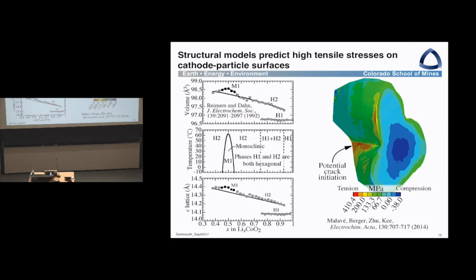What's interesting about this is if you look at the lattice spacing, there's actually a considerable change in the lattice spacing as you intercalate, and it goes in a direction opposite from what you might think. You would intuitively think as you push lithium into this matrix, it would blow up like a balloon. In fact, that's not what happens. The lithium, since it's a positively charged ion, tends to attract the anions, the oxygen, and so it actually shrinks a little bit, with a fairly substantial difference between the lattice volume of these two hexagonal phases.